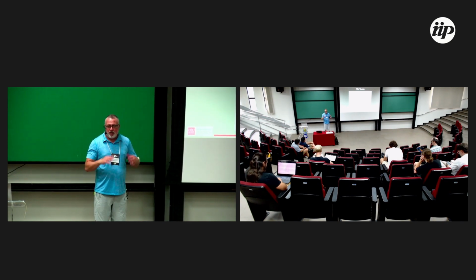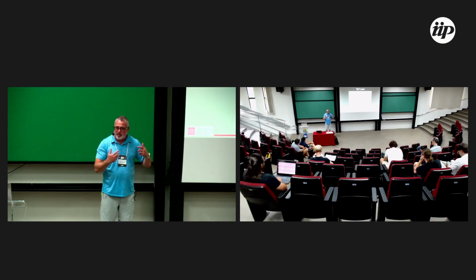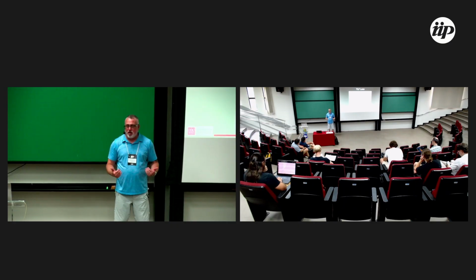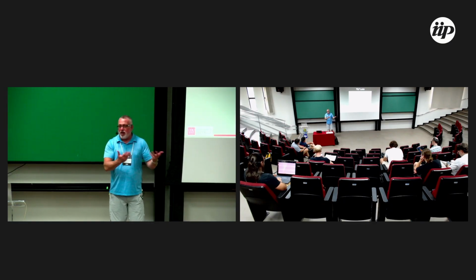Yeah, no, that's a really interesting point. Before we jump to Greg, I wanted to point out another piece that I think, not for the data set here, it's maybe too high temperature, but as one moves towards still fridge temperatures, something I'm curious about, and Greg may talk about this in his guided discussion, is that there's also the coherence time of the defect spins to take into account. Because eventually, if those times, and the magnons, right, get to be long compared to the scattering time, then you can have an additional effect where everything just synchronizes. In my mind, I think of it as the magnons recruiting the defect spins into the magnon, right? If everything's super long-lived, then you only have to scatter once, and then everything's in sync for a long time after that. And that also could show up in a reduction of loss, because you're still coupled to the same bath, but that isn't a lossy interaction anymore.